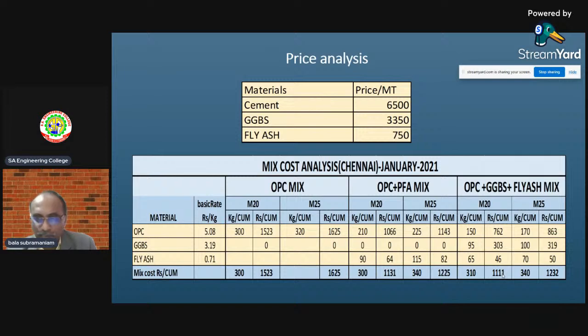The same difference applies here, but let us not see the fly ash mix and blended mix together. Let us make it a little simple. Even with the M25 customer, where he buys at 1,625, here it is 1,225, a 400 rupees difference. Even with the blended form, the difference is huge. Where a customer uses 1,225, when it's a triple blend, that is OPC, GGBS, and fly ash, it is 1,232. It is not a big difference, but still you have some difference there, 10, 15 rupees. But in this case, if you use triple blend mixes, you will have characteristic strength differences. You will have higher strength.